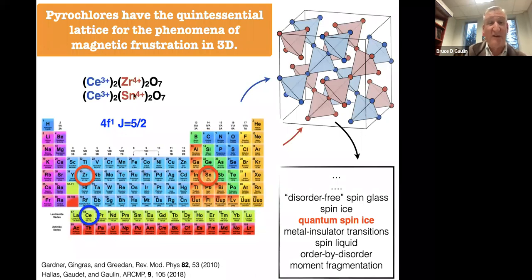Zirconium 4+ and tin 4+ are both non-magnetic. Zirconium 4+ has the electronic configuration of krypton, so it's a filled inert shell configuration, so no magnetism. And tin 4+ is similar, except that it's got a filled 4d shell. And so we decided to focus on cerium 2, zirconium 2, oxygen 7, because we felt it was likely we could grow single crystals, and this turned out to be correct.